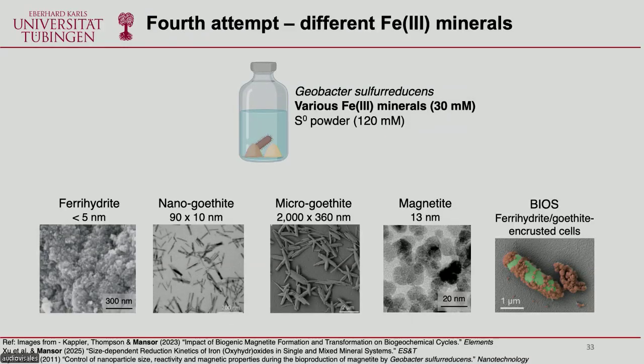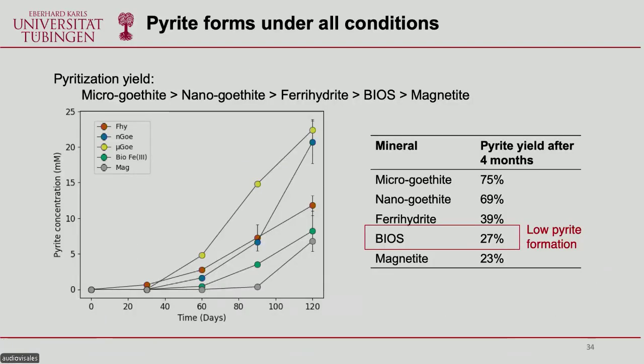But we can play around with something even more. We know that in the environment, there can exist different types of iron minerals, and we tried 5 different types that we synthesized in the laboratory. We can try very small ferrihydrite, goethite that can have 2 different sizes, we can try magnetite, and we can even try the encrusted cell. By doing all of this, we show that we have a recipe to form pyrite at ambient temperatures under all conditions, no matter what type of iron minerals we use. But what's interesting is that they all produce pyrite at different rates and to different extents. One thing I want to highlight is that using the encrusted cells, the BIOS, we see quite low pyrite formation. We think that some organic matter is inhibiting pyrite formation, but this is still being studied.